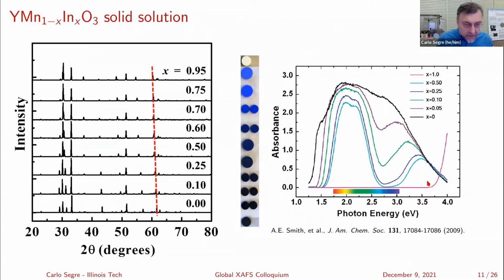So the one nice thing about the yttrium manganese indium material is that you have a full solid solution range, and you can make it all the way from pure indium to pure manganese, and it maintains the same hexagonal structure. That's not always the case for all the other ones. They're a little bit tougher to make this way, and you can't always make them over the full range.